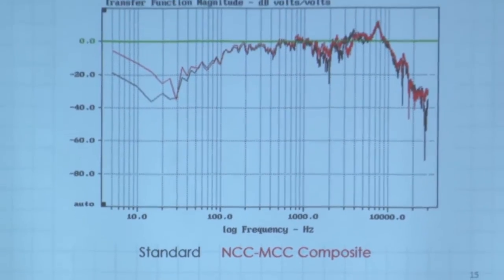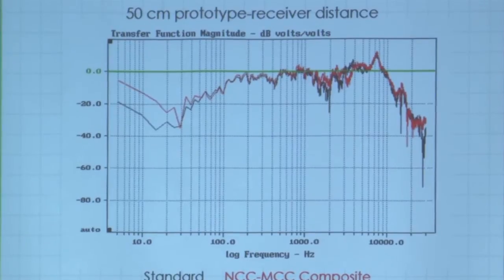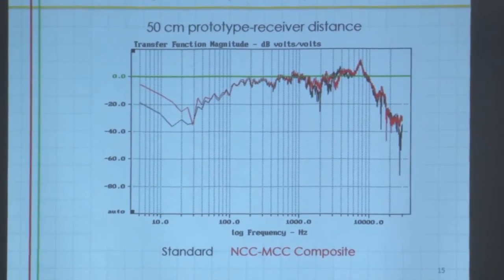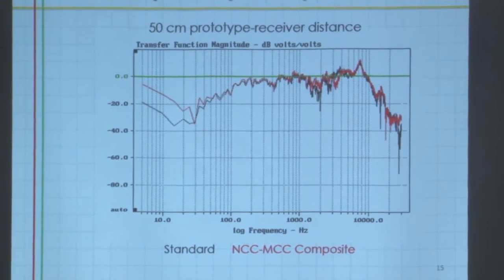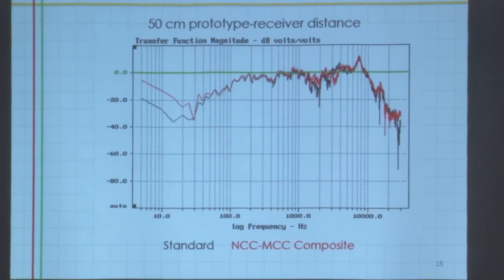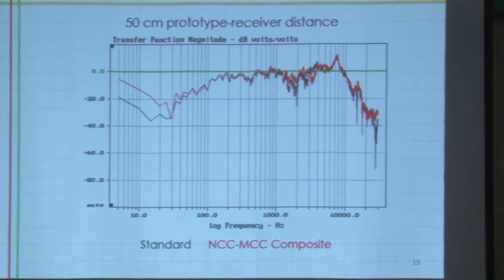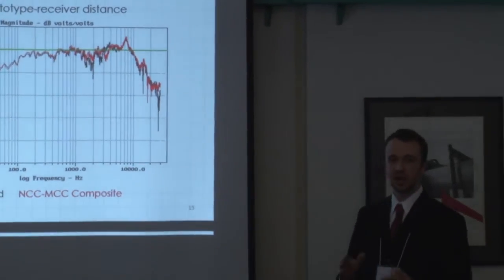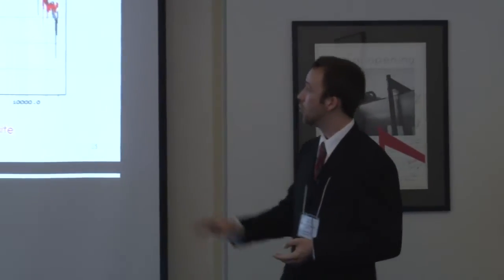This is our data. So in this particular setup, we had our prototype placed 50 centimeters away from the high fidelity microphone. Red shows the performance of our composite, the black shows the performance of the standard, and that green line that you see up there at the top is the ideal perfect flat response that a perfect speaker would give. What you see is a great deal of overlap. This suggests that the NCC-MCC composite may be useful in audio applications.